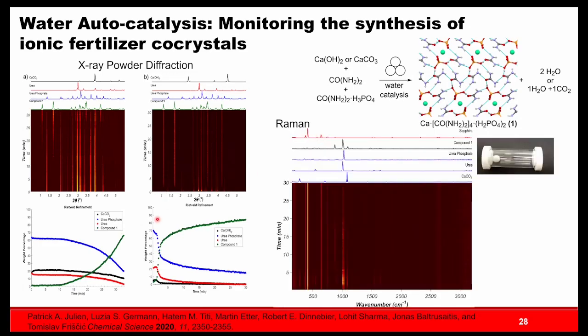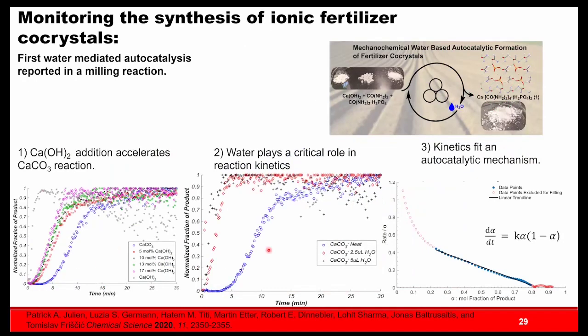Actually this was the synchrotron data we took, but we wanted to do more experiments. So we then moved to Raman spectroscopy in our lab, where we were able to do a lot more experiments. And using some new sapphire jars that we developed, you're able to look at this reaction reasonably efficiently and get the kinetic values.